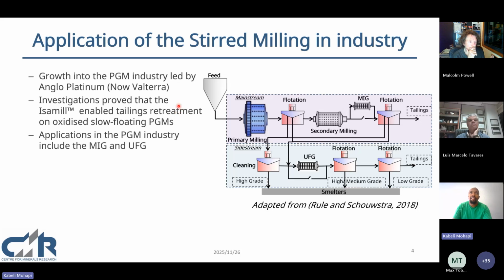The application of stirred milling in the PGM industry, or rather in the mineral processing industry, has seen significant growth, inspired by Anglo Platinum, which is now Valterra. They, however, utilize an ISA mill, which has been proven to enable tailings retreatment on oxidized and slow floating PGMs. Its application in the PGM industry includes mainstream inert grinding, where they optimize recovery, and ultrafine grinding, where it is utilized to optimize grade.